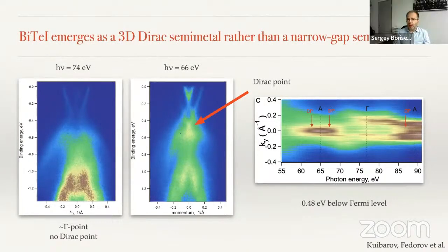Yeah, I think the surface states are always here. We have done a lot of slab calculations. The surface states are also present, but we think they are sitting actually here. I showed them in the earlier plot of the valence band, where it was pretty clear that the surface state did not coincide with the bulk bands. So surface states should be there, but they are not topological surface states. That's why they're not robust as in bismuth telluride or bismuth selenide. And our experience is that a non-topological surface state could be a very fragile object. They could turn up, they could disappear. It depends on many factors.